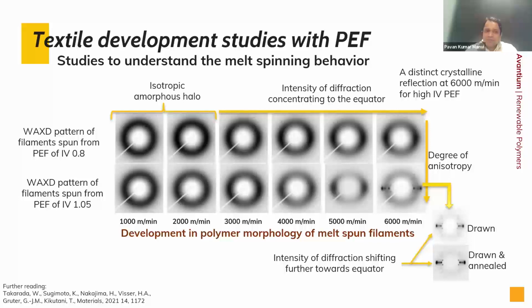But in the case of IV 1.05, as we learned in the basics, at the higher IV the chain interactions are higher, and therefore the mobility is hindered, and faster crystallization can start. Due to the crystallization around 4,000 meters per minute, the intensity is moving well towards the equators, and this becomes very prominent at the higher spinning speed. So there is a comparison with some fully drawn and annealed samples.